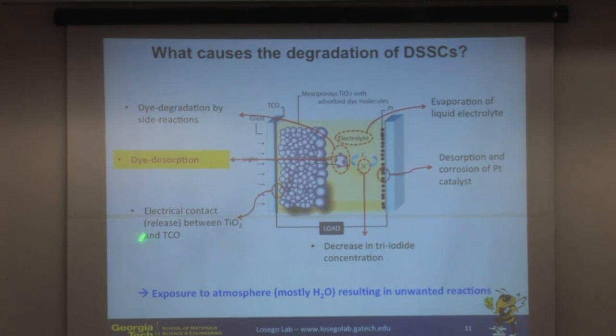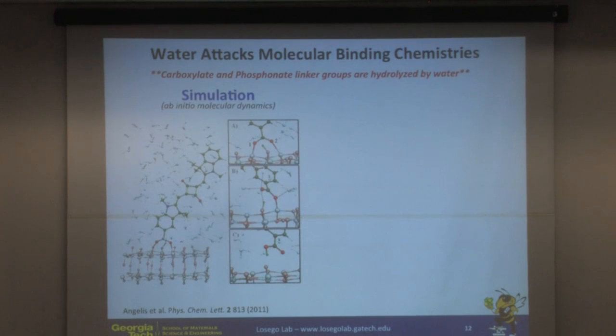So if we look at this, there's a number of mechanisms for degradation, but probably the most important fundamentally is the desorption of the dye from the surface. If we lose the dye, we're no longer going to be able to transfer that charge upon light absorption from the dye to the inorganic species. And the reason dyes desorb primarily is due to water. Water attacks the binding chemistry between the dye molecule and the inorganic surface.